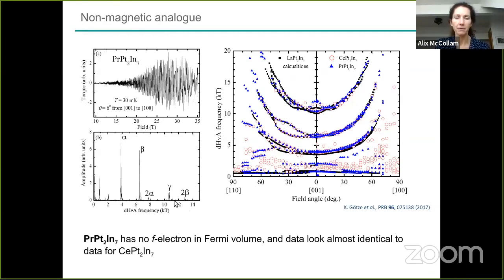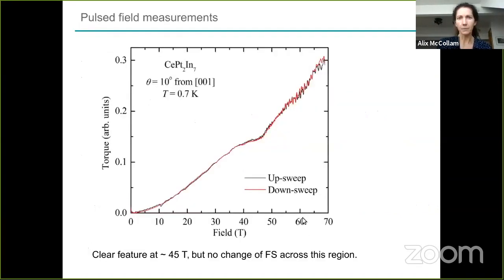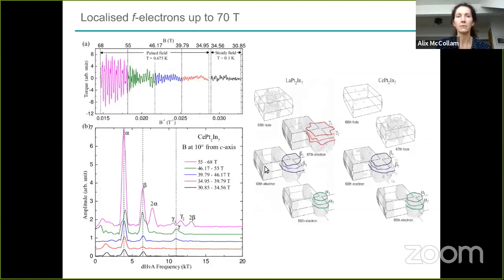The frequencies are similar, and you can see that the blue is the praseodymium compound and the red is the cerium compound, and they're really identical. They're sitting right on top of each other. So to us, this is rather convincing evidence that the f-electrons are localized and the Fermi surface is small, all the way up to very high field in cerium platinum 2 indium 7. We did also pulse field measurements up to 70 Tesla to confirm, to look at this 45 Tesla feature and to see what happens there. But we see also no change right up to 70 Tesla.